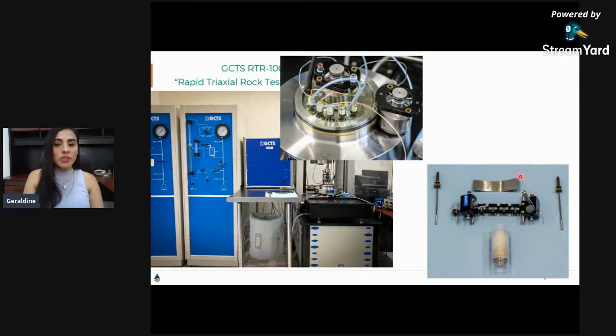Then another component of a triaxial cell is the sensors. These ones here are called LVDTs, axial LVDTs, and they are placed on both sides of the sample in order to measure the axial strain or axial deformation. And then you also have a radial LVDT. This is placed around the sample and measures the radial strain. As you can see here, this is my sample. Our samples are cylindrical, called blocks.